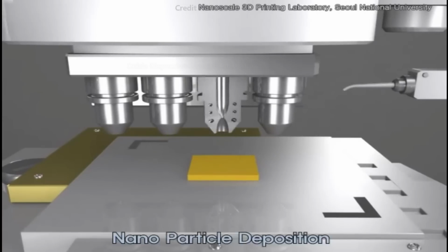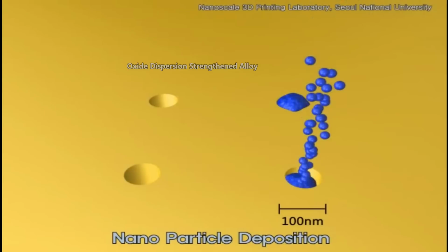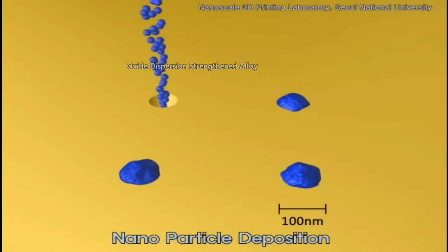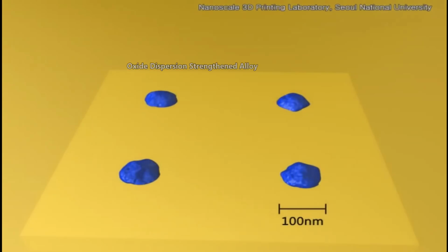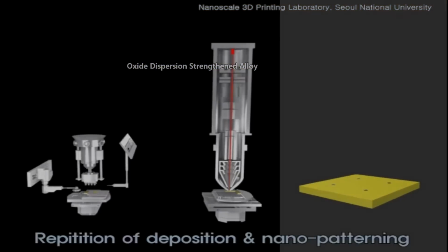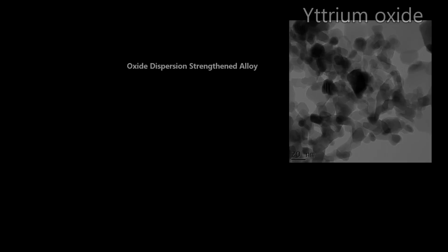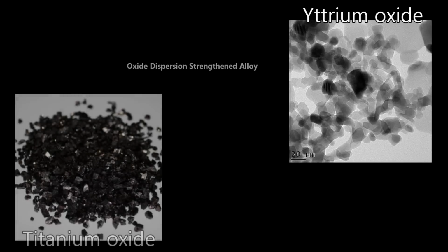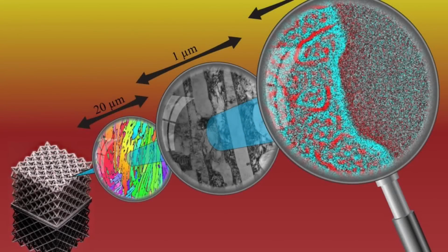GRX-810 is an oxide dispersion strengthened alloy, also called ODS. This means it is a class of materials that combines a metal matrix with small and uniformly dispersed oxide particles. These particles are usually composed of yttrium oxide or titanium oxide, uniformly distributed within the metal matrix. The particles act as strengthening agents and effectively hinder dislocation movement, enhancing the alloy's strength and resistance to deformation, allowing these alloys to have excellent mechanical strength and creep resistance, thus preventing grain growth and maintaining strength even at high